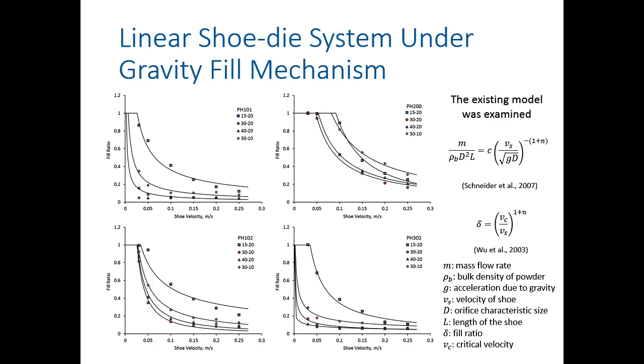Using the model developed by Schneider, we basically fitted the model to the experimental data, calculated the exponent n, and used the model developed by Wu to basically predict the behavior of the powder, as you can see by the continuous lines on the figure. So we can see that the model can predict the behavior really well.